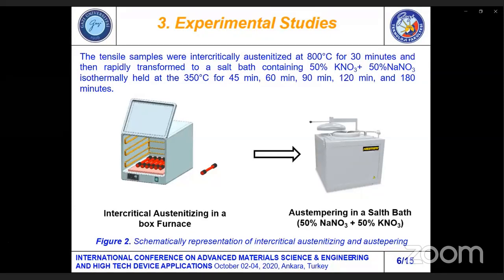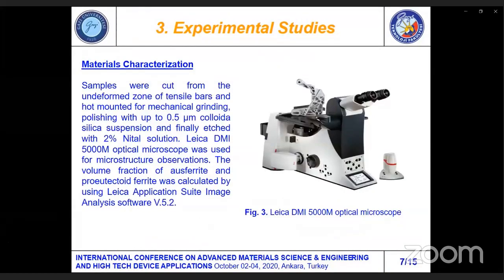Here you are seeing the schematic representation of the box furnace used for intercritical austenitizing, after which we rapidly transferred the tensile samples to a salt bath. You are seeing the schematic representation. Materials characterization samples were cut from the undeformed zone of tensile bars and hot mounted for mechanical grinding and polishing up to 0.5 micron colloidal silica suspension, and finally samples were etched with 2% nital solution. We have used a Leica DMI 5000M optical microscope for microstructural observation. The volume fraction of ausferrite and proeutectoid ferrite was calculated by using Leica Application Suite image analysis software version 5.2.